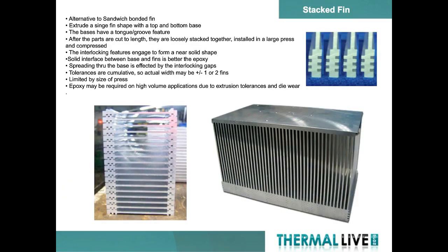Another alternative when you're looking specifically at a sandwich-style bonded fin is what we call our stacked fin product. Here what we do is we extrude an I-beam. And the base and at the tip, you have an interlocking set of grooves. The parts are stacked together. The part is compressed so that the interlocking grooves lock with the mating features. And now you have a singular heat sink stack that can be machined.